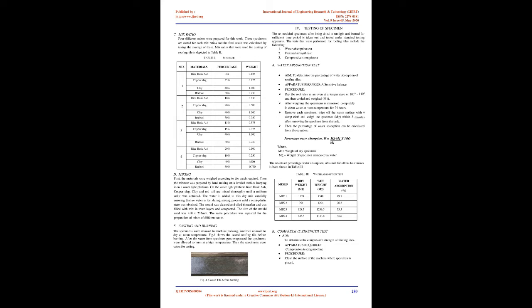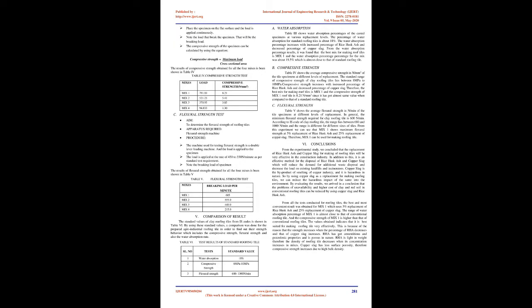The compressive strength of the specimen can be calculated by using the equation. Compressive strength equals maximum load divided by cross-sectional area. The results of compressive strength obtained for all the 4 mixes have been shown in Table 4. Table 4. Compressive strength test. Mixes. Load. Compressive strength, N/mm2.